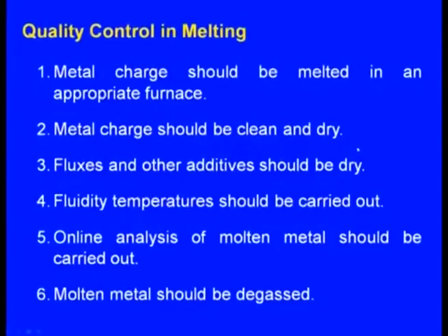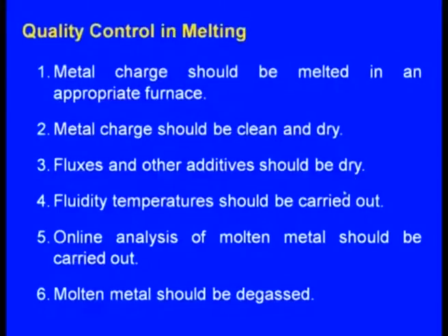Sometimes it is possible that people take the scrap and dump it in the furnace, and this scrap may contain unwanted oils, lubricants and so on. Then the composition will change, or hydrogen will evolve because of the carbons or the hydrocarbons present on the surface of the scrap. So, the metal charge should be clean and dry. Fluxes and other additives should be dry. If moisture is present, it must be dried out before they are used.